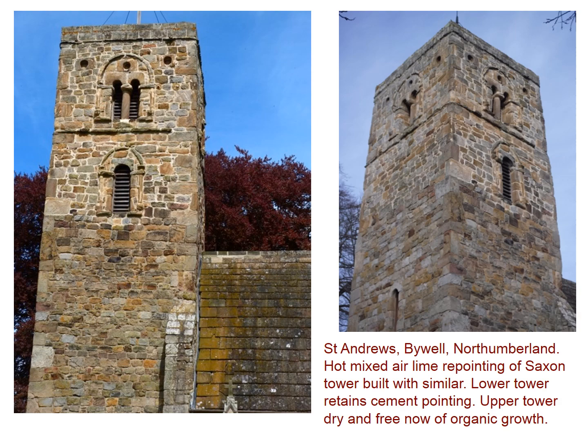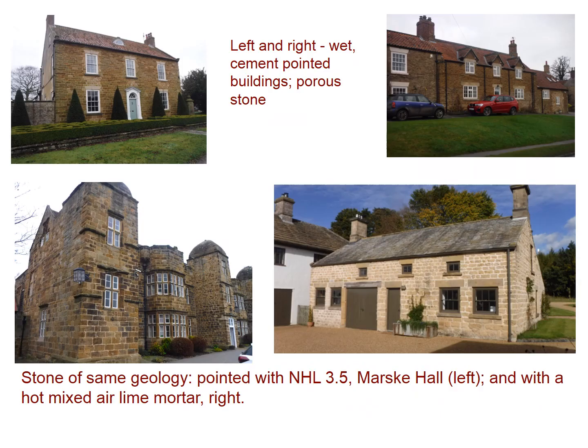It wasn't cleaned at the time of repointing. It has self-cleaned as the stone and the fabric has dried, preventing algae and lichens from getting a foothold, unlike on this cement pointed material below. Left and right, wet cement pointed buildings, porous stone in both cases. Bottom left, Marske Hall, grade 1 listed, perennially wet. This photo wasn't taken on a rainy day. On the right, a building of very similar geology of construction, but repointed with a hot mixed air lime mortar.